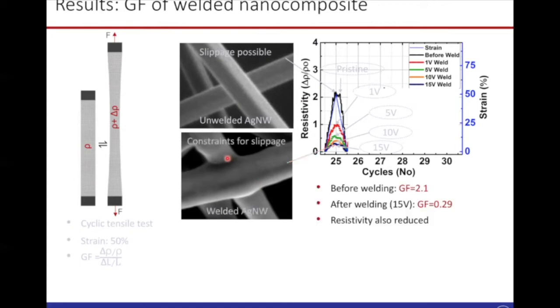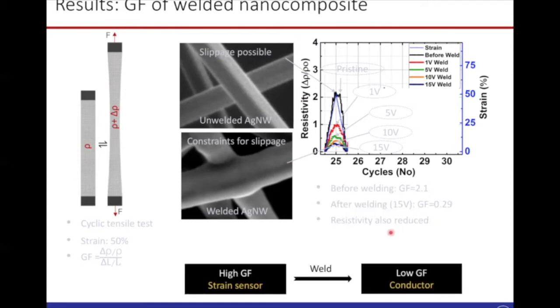And at the end of the welding, I would like to say before welding, you had a gauge factor of 2.1. And after welding, you have 0.29, close to 0. So the gauge factor is reduced. Also the resistivity reduced and the sample became more conductive. So we can say the strain sensor-like behavior is now switched to a conductor-like behavior, and that means you can fabricate both strain sensor and conductor using a single material.